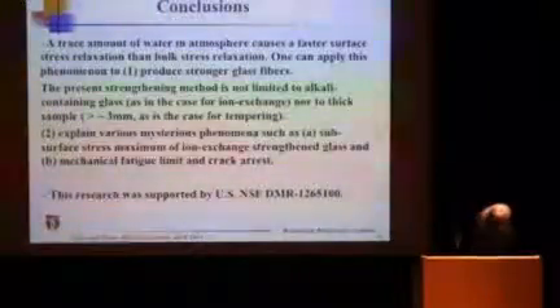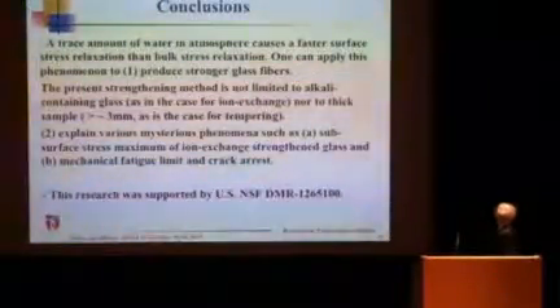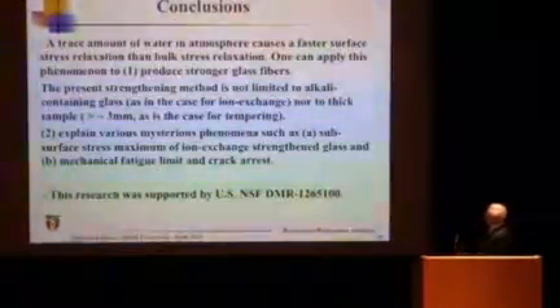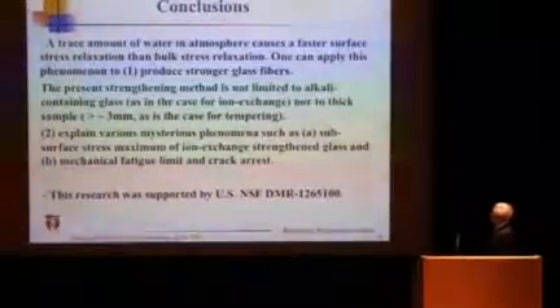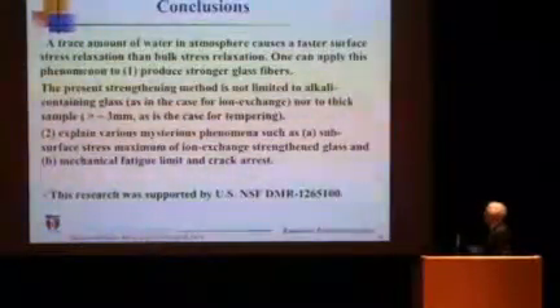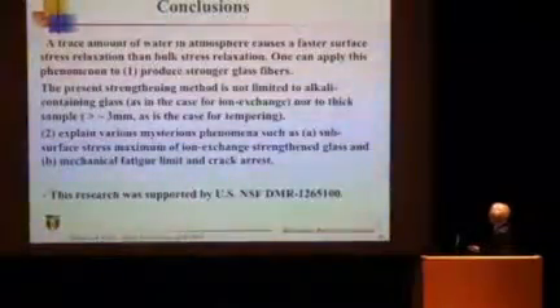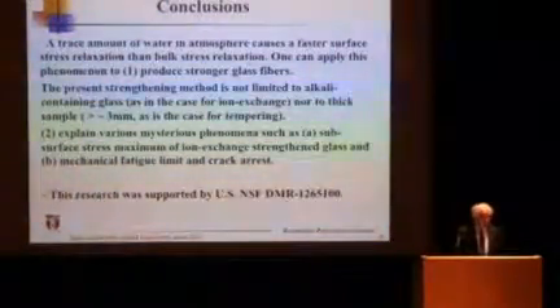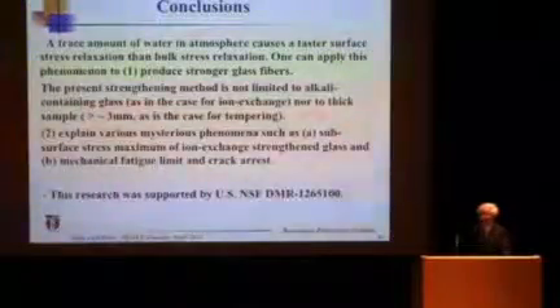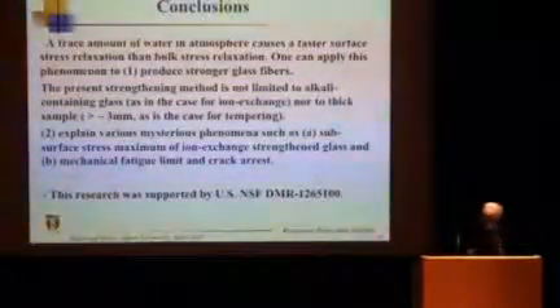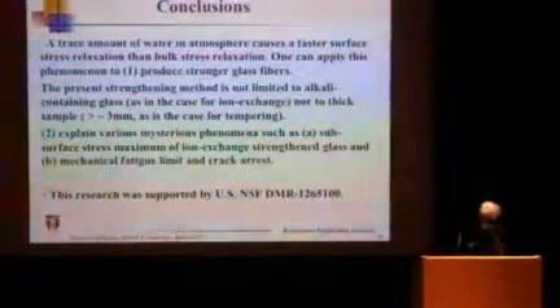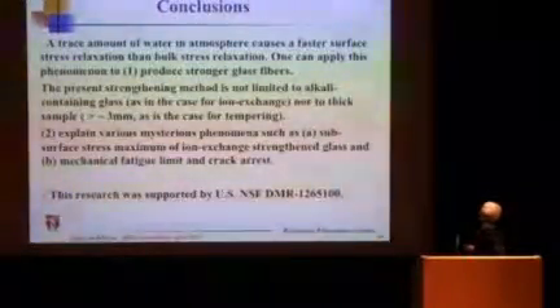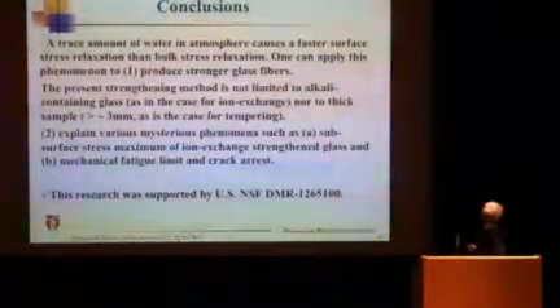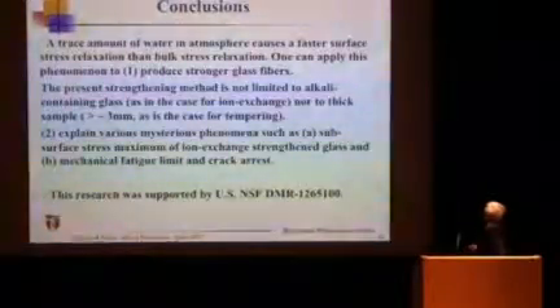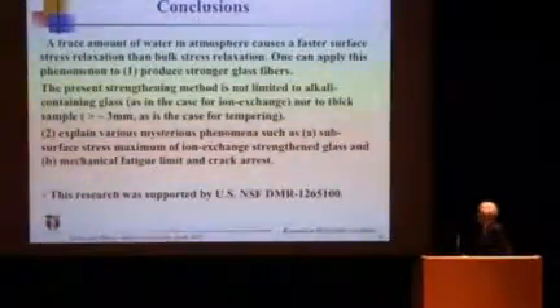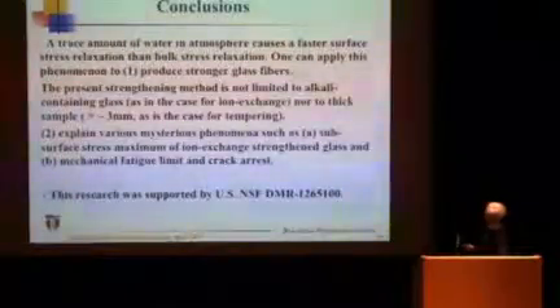So in conclusion, I can say the trace amount of water in atmosphere causes a faster surface stress relaxation than bulk stress relaxation. The surface stress relaxation concept has not been recognized, not discussed, so I don't think you'll find it in Web of Science. And we found this can apply to make stronger glasses, and that method is applicable to all kinds of glasses, not limited to the thickness.